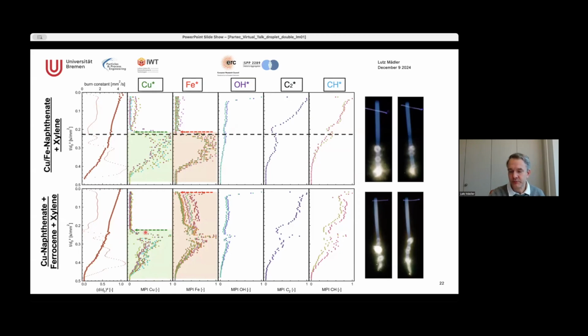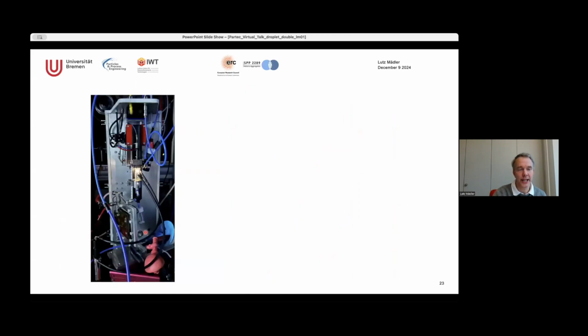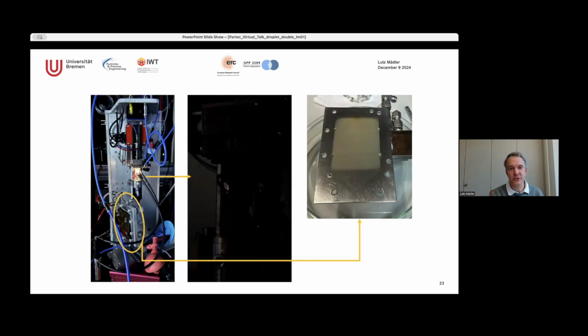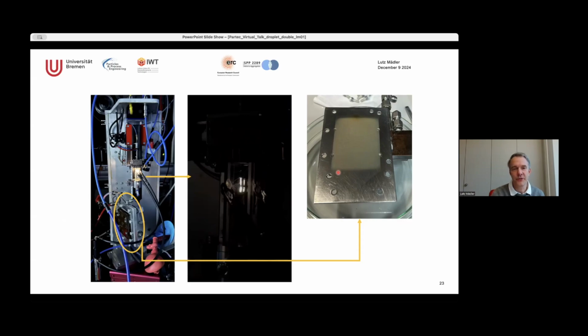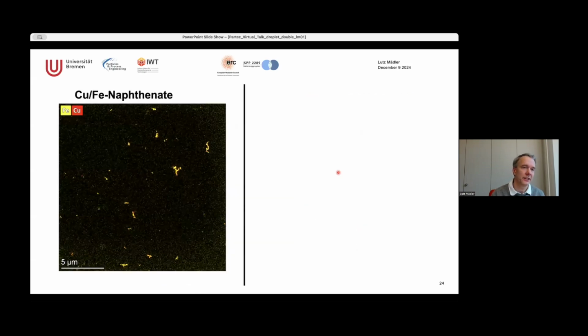All right. So Jan was able to collect in single droplet experiments. So you really have to imagine these are droplets smaller than 100 micron. And then each droplet comes out, and then you need to collect the particles from these very tiny droplets. So it took him a while. So he was successful and he listens to some music too. And he was successful in actually collecting some of these powders. And he did the analysis in the high resolution TEM.